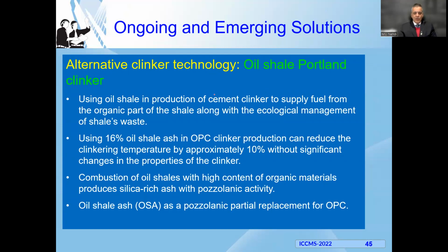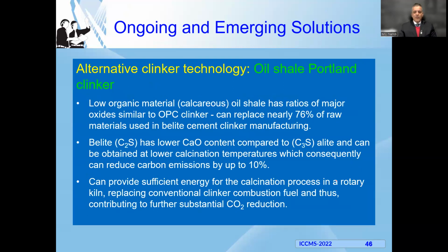I will start with one alternative clinker technology, the oil shale Portland clinker. So what is this? Essentially, we will be using shale that contains oil as an ingredient that we put in the kiln. So not only do we now have the shale as an ingredient in the cement production, but we have that part of it that is energy, oil, that should be reducing the energy demand for cement production. So using, for example, 16% oil shale ash in ordinary Portland cement can reduce the clinkering temperature by approximately 10% without significant changes in the properties of the clinker. So it could be a pozzolanic material, and yet also providing energy for reducing cement production.